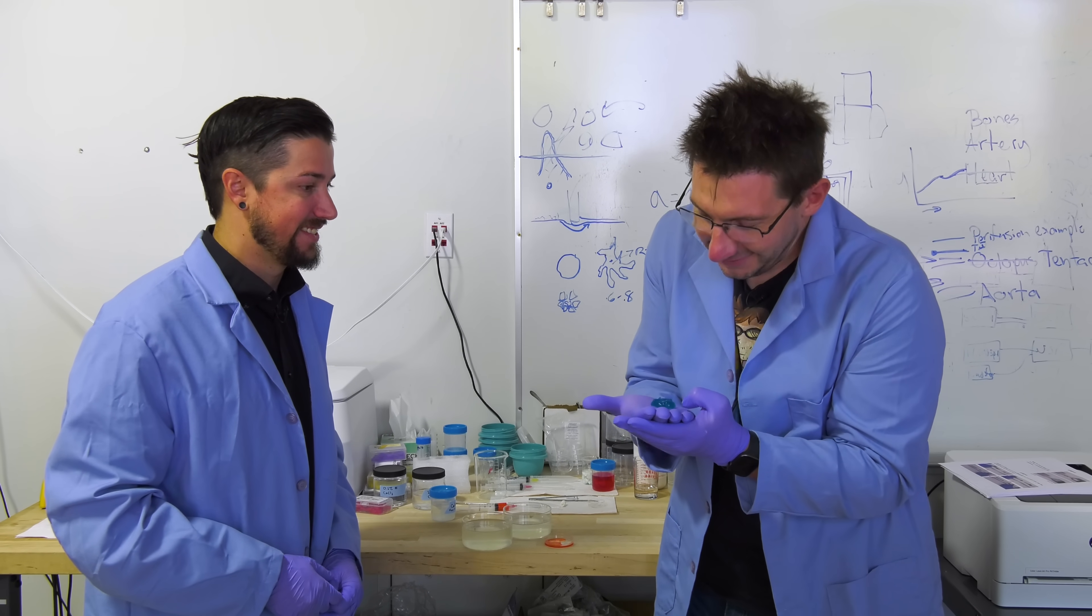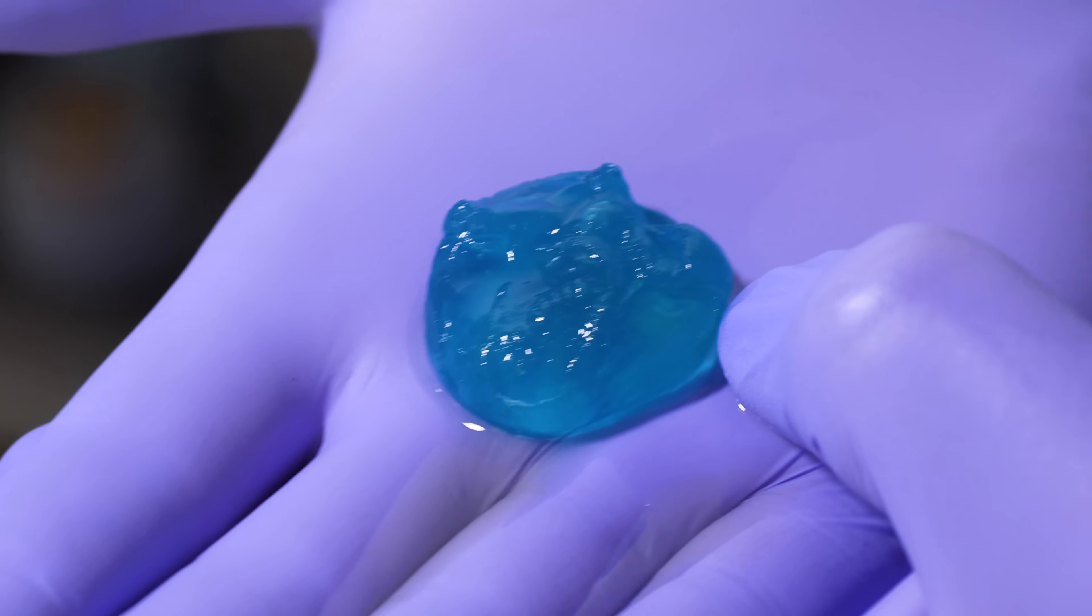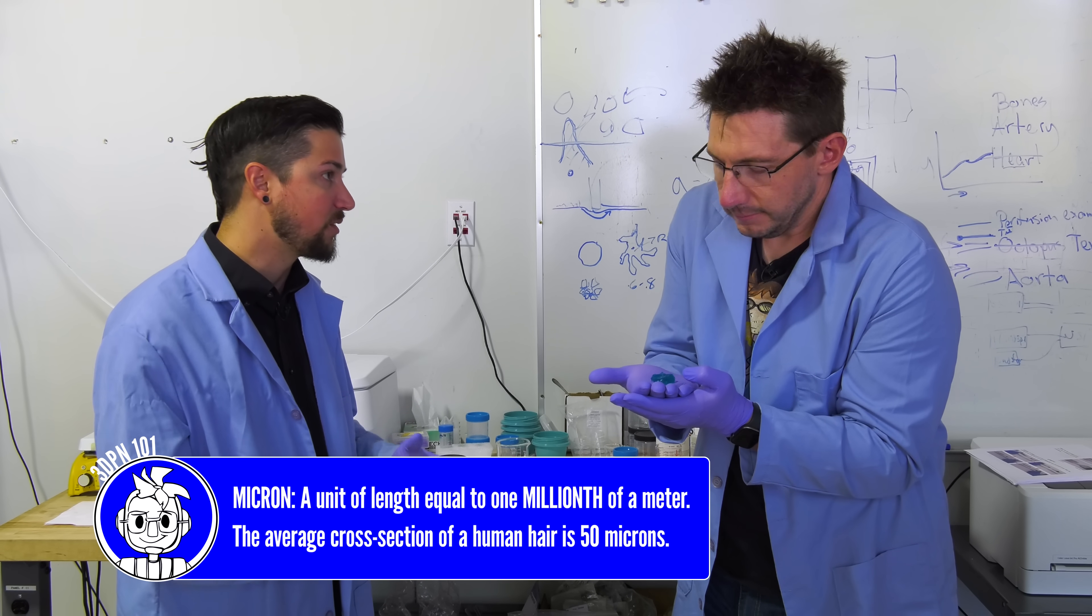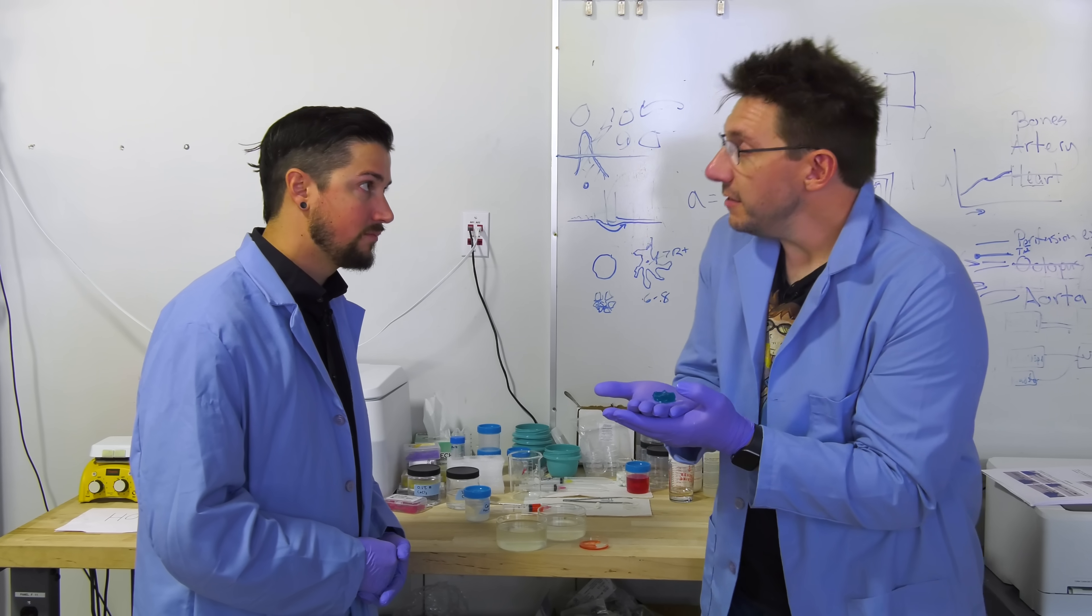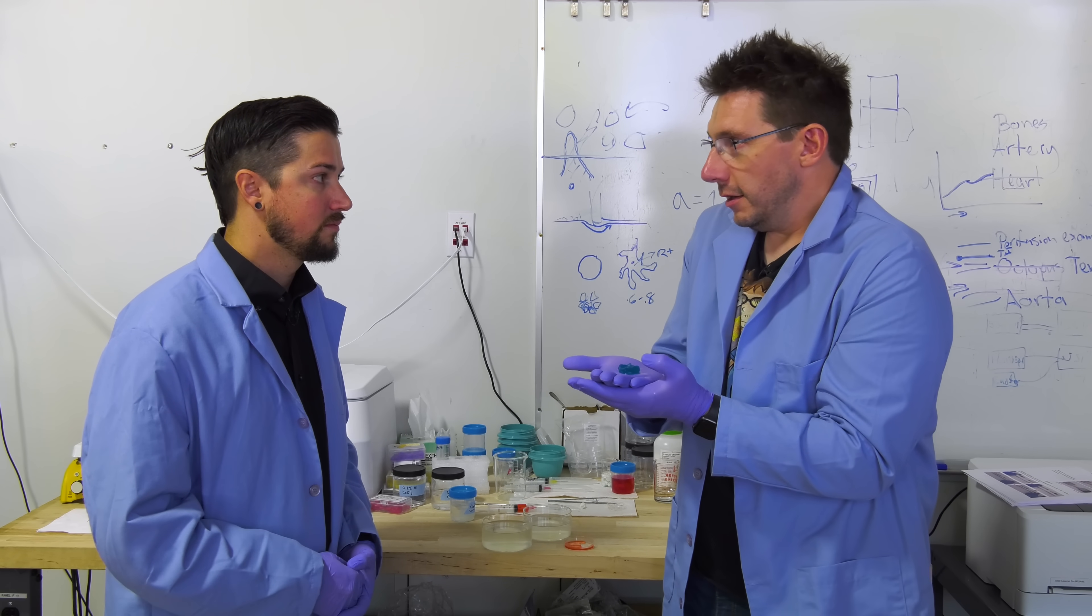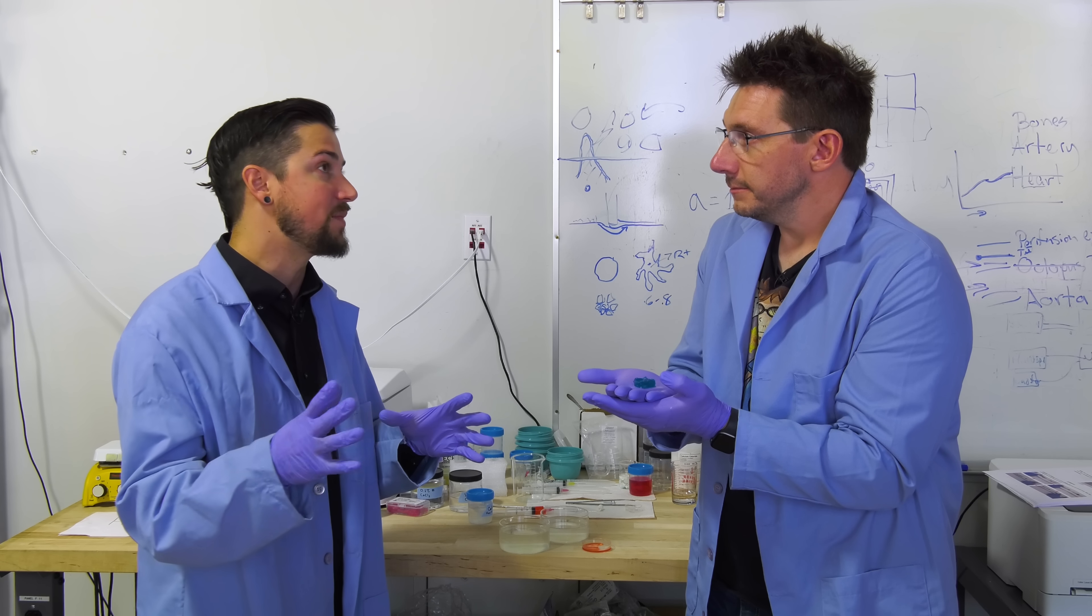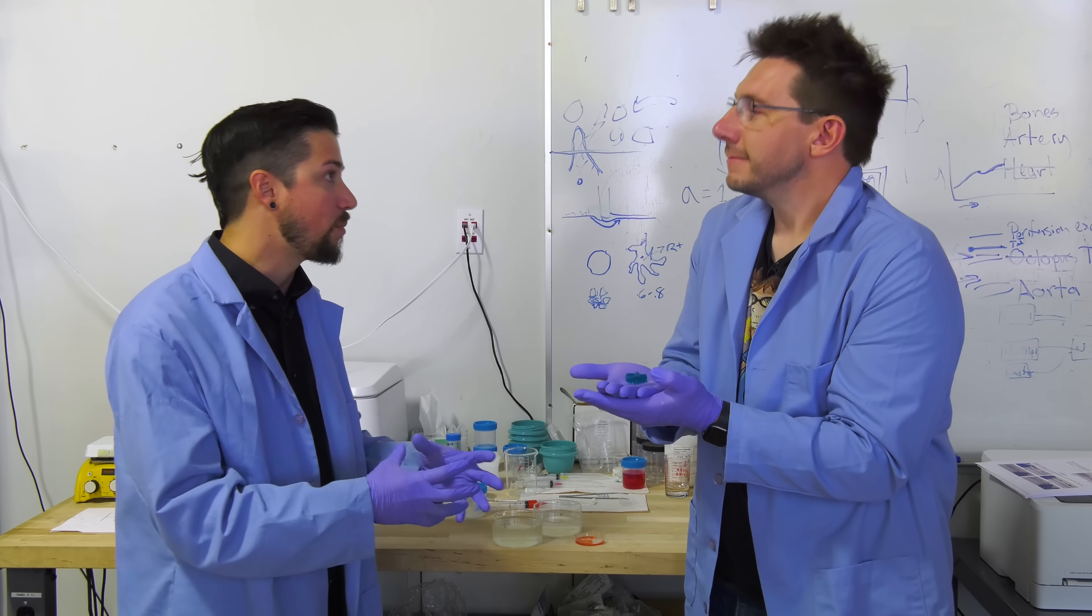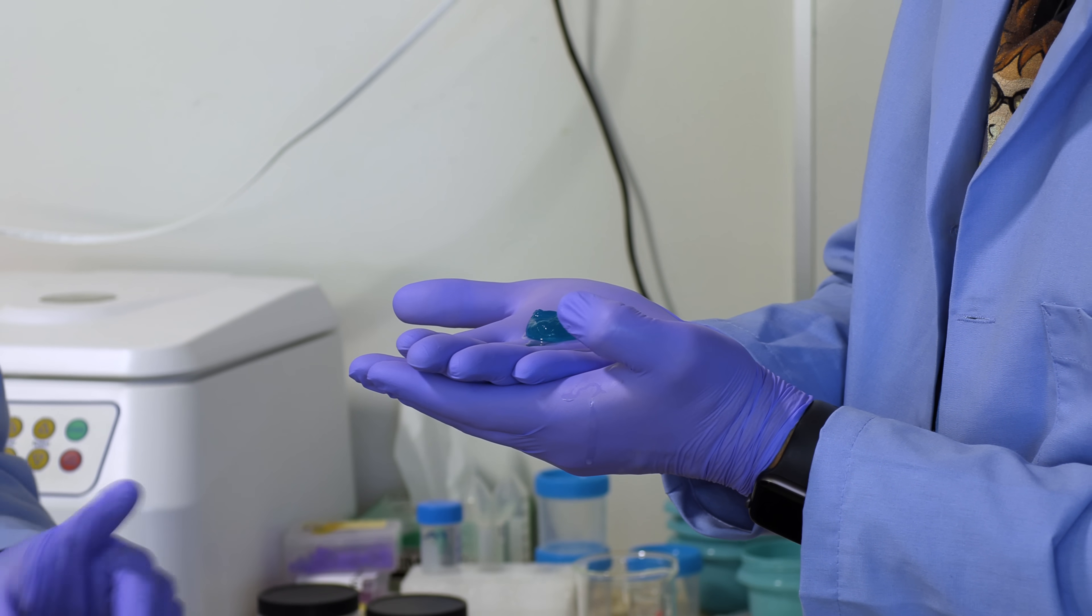How's it smell? It smells like a doctor's office. You can see the detail, like the small detail of this. Yes. So we're actually able to go down to 5 micron layers and we're able to go down to 20 micron needles. Although when you do living cells, you can only do about 100 micron needle because then you start to impact the cell viability or you start to kill the cells. Really? So too small of a needle and the cells die. Yes. This is a heart, meaning if it was okay, this is the prototyping material, then you could use living cells and make a heart that is compatible with like a living organism. Yes, that is the end goal. You would use collagen and a couple other things that comprise of the, or make up the extracellular matrix. Basically, cells by themselves do not make up tissues. There's a whole lot of extra material that help those cells form a structure and talk together and work together to do their function. And that's collagen, that's fibrin, that's hyaluronic acid. That's a whole lot of stuff. Yes.